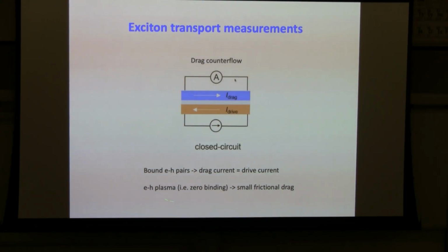On the other hand, if you have no exciton binding, meaning that it's an electron-hole plasma, then at low temperature, you would just get negligible drag current. Even if you drive very hard, you get just no current on the other layer at low temperature.